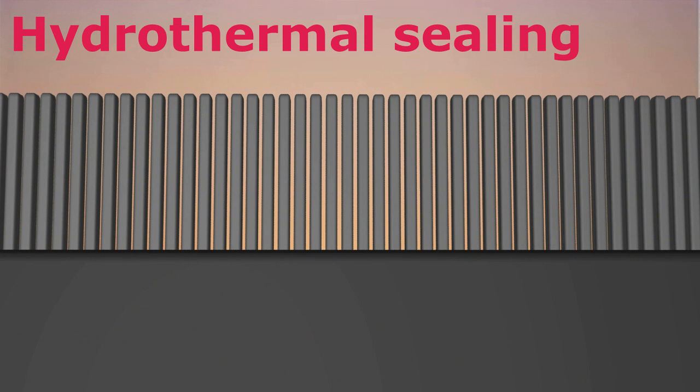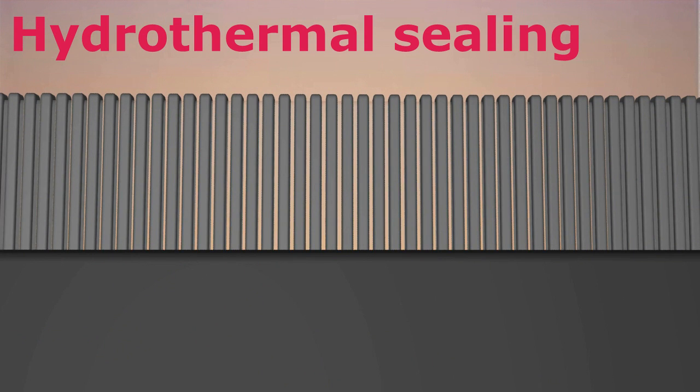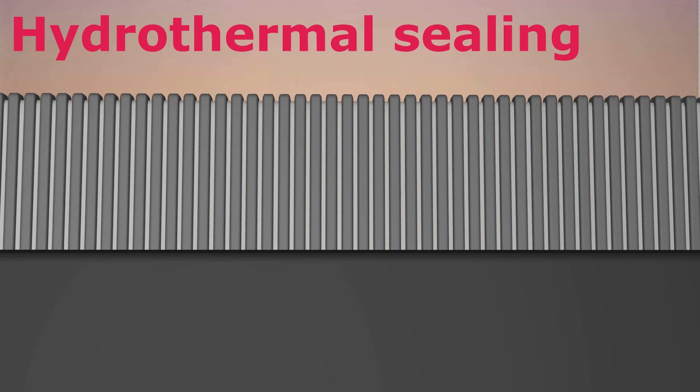As a result, some aluminum oxide is turned into aluminum hydroxide, which takes up more space, and therefore completely seals the nanoscale pores.